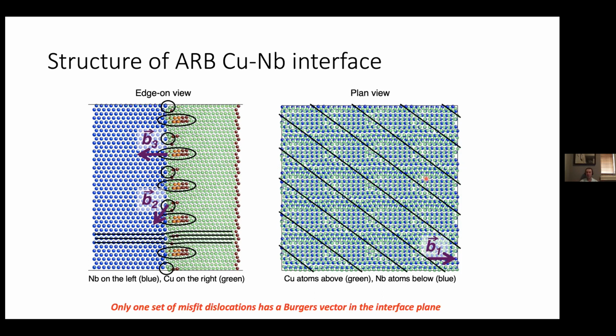But maybe just to assuage your curiosity, there are actually rigorous ways of showing that these dislocations are indeed present in these interfaces, as well as figuring out what their Burgers vectors are. And this particular set of dislocations has a Burgers vector that is contained entirely in the interface plane. So in other words, we have two sets of dislocations with Burgers vectors that point out of the interface plane, one set of dislocations with the Burgers vector that is in the interface plane.